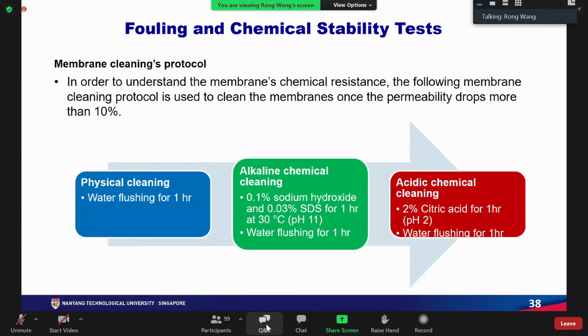We also do long-term testing to understand the fouling impact and also chemical stability. We know the membrane needs chemical cleaning. We wonder if our membrane is stable when we use chemical agents to do the cleaning. So we follow the standard protocol for membrane cleaning: physical cleaning, followed by alkaline chemical cleaning and acid chemical cleaning. These are the standard procedures. Now, here are the results.